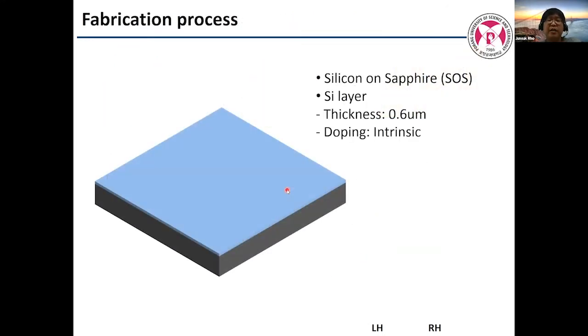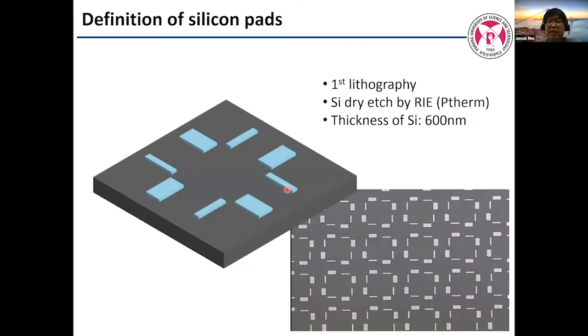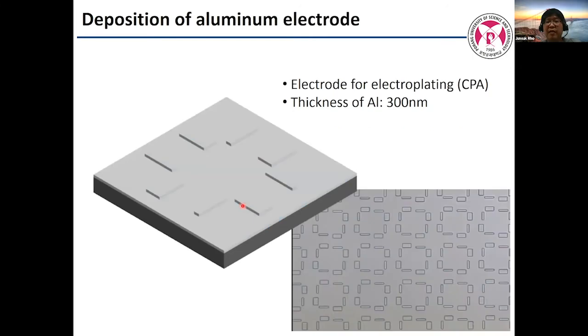As I mentioned, this is microfabrication, and the unit cell size is about 50 micrometers. This is a mask, the top view design, and this is a hole. We first do lithography on a silicon-on-sapphire wafer. This is the first lithography and etching of silicon, giving a bottom pad of silicon. Then we coat with aluminum for the next step, the fourth step, where we do electroplating. So we need the electrode at the bottom.